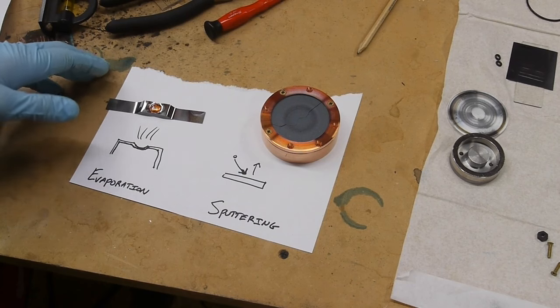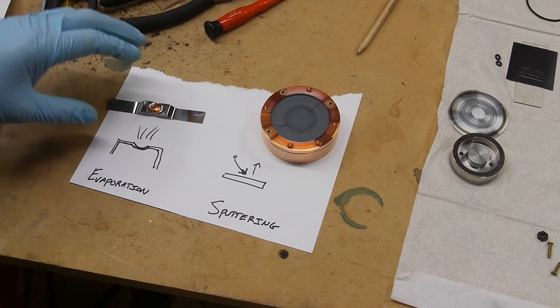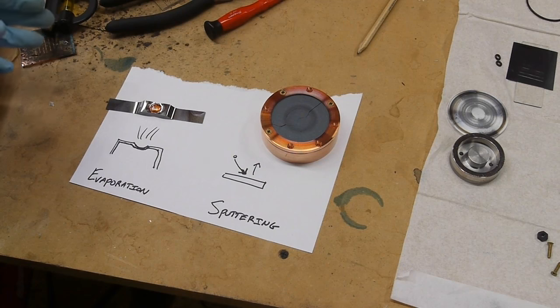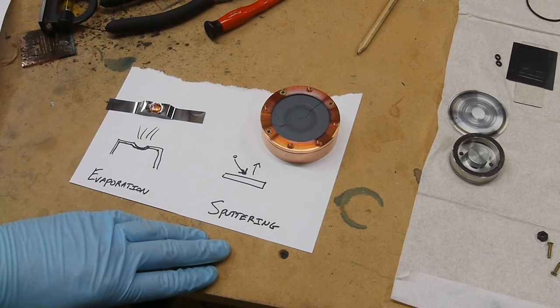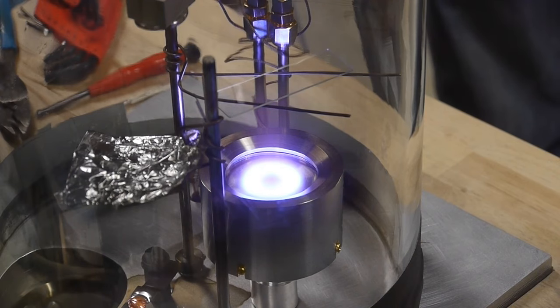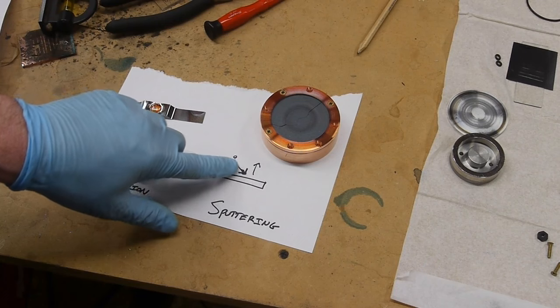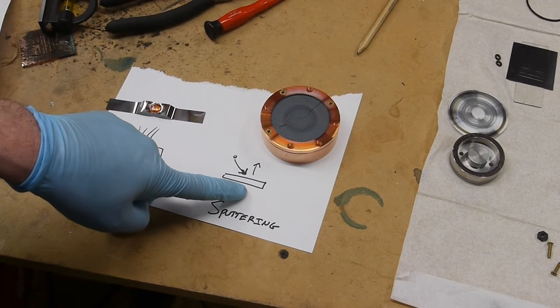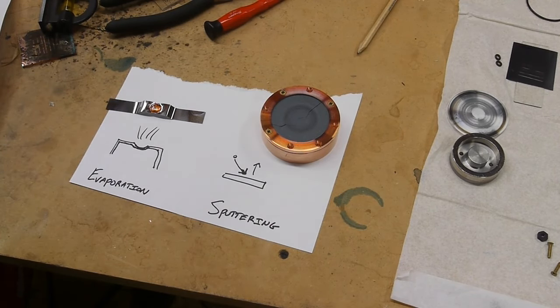The downside with this is that you have to heat up the material to that yellow hot temperature. So if your material can't take it or if it changes into another material at that temperature, then this isn't going to work. When we're talking about making conductive ITO coatings, this is definitely the case, where if you heat ITO up in a vacuum it reduces itself back down to base metals. An alternative process is called sputtering, and this works by accelerating gas molecules and slamming them at very high speed into the surface of the material. When that happens at just the right energy levels, it chips off a few molecules from the surface, and they go spraying off into the chamber and eventually land on the thing you want to coat.